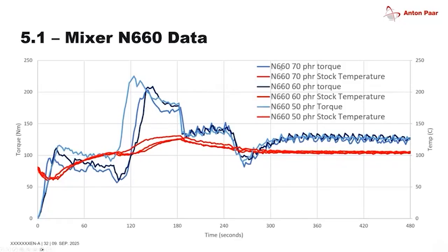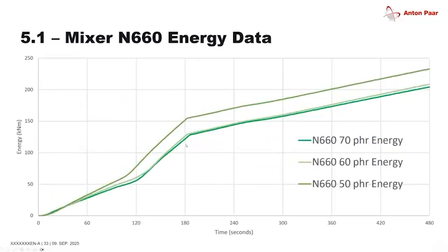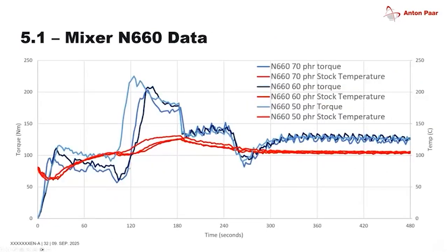There was especially between the first two, not so much, but you also have to be considerate if the operator, and you see here the minimum, was able to fill this slightly early, this makes this shift. So operator bias still has to be considered. Temperature is pretty identical because we ran the temperature program. We can see here by the energy. So our software also gives you how much energy in kilonewton meter or kilojoules is applied over the time. And this follows directly what you saw here with the torque.